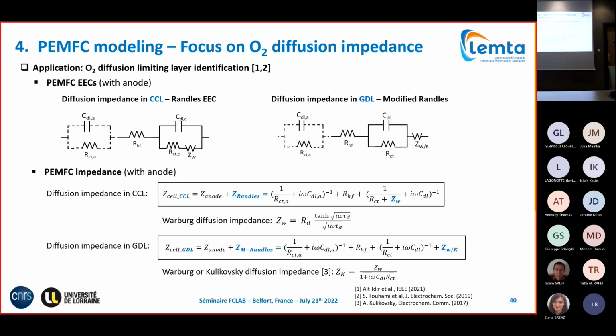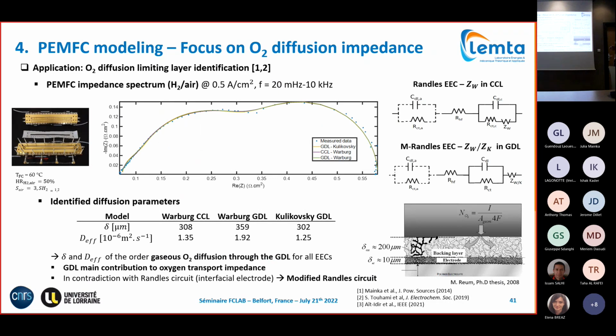As hydrogen is diffusing very fast, we do not need a diffusion impedance. Okay, here you see the spectrum measured. Blue dots here are from one of our cells. Here you see the different fitting curves obtained with the different models. And this shows you that we have identical fitting curves.